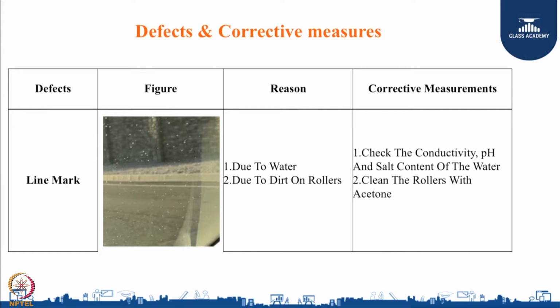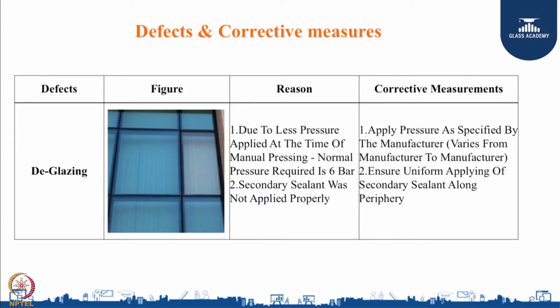Now let us understand one by one. Line mark. The reason is very simple: quality of water or dirt on rollers. Corrective measure is check the conductivity, pH and salt content of the water, clean the rollers with acetone, and you can avoid line mark. Deglazing. Reason is less pressure applied at the time of manual pressing, because normal pressure required is 6 bar. Another is secondary sealant was not applied properly. Corrective measure is apply pressure as specified by the manufacturer. Ensure uniform application of secondary sealant along the periphery, and you can avoid deglazing.